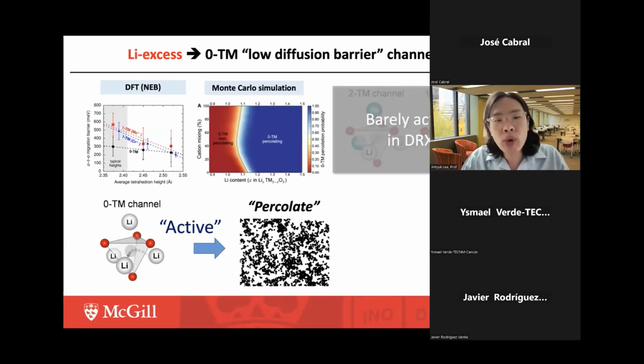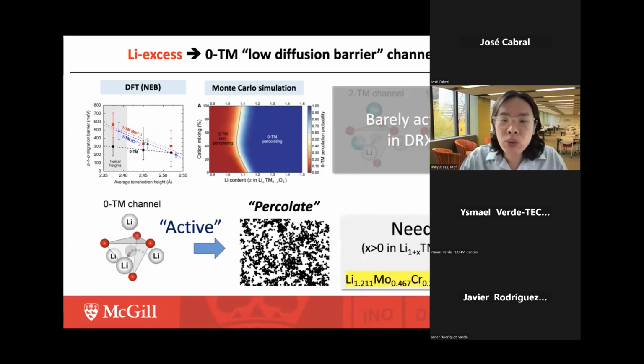And what we found from the Monte Carlo simulation is that in order for this 0-TM channel to occur, the disordered rocksalt materials have to be made into so-called lithium-excess materials, where lithium excess stands for the composition in which the number of lithium sites is greater than the number of transition metal sites, such as the Li1.2 transition metal 0.8 O2 composition.